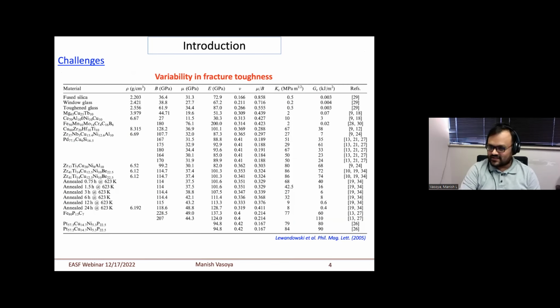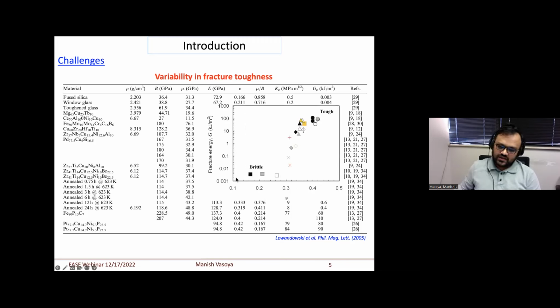But the key challenge in this material is the variability in the fracture toughness. Here I'm showing you literature papers showing different materials, meaning different compositions of bulk metallic glasses, and how the toughness varies. I'm also showing some of the same composition but with different processing, like annealing at different temperatures or at the same temperature but for different hours. It shows a very huge variation in the fracture toughness, which we can see in this plot, where I plotted, from this paper, fracture energy versus Poisson ratio.